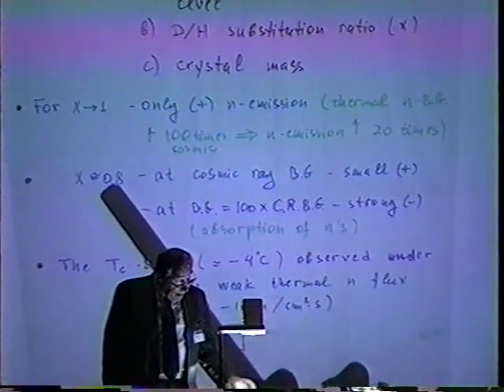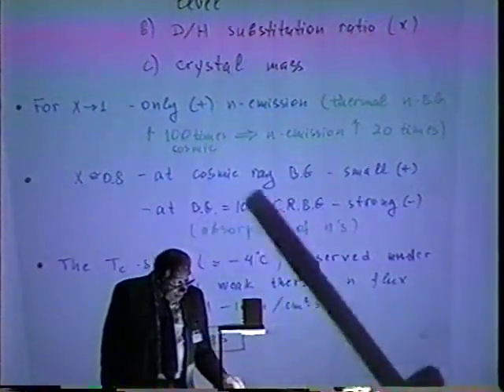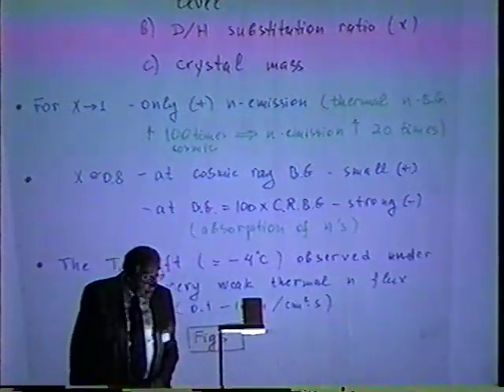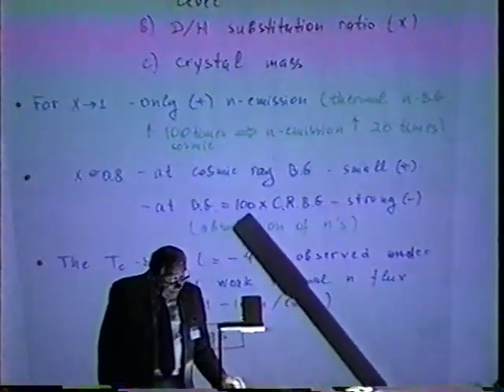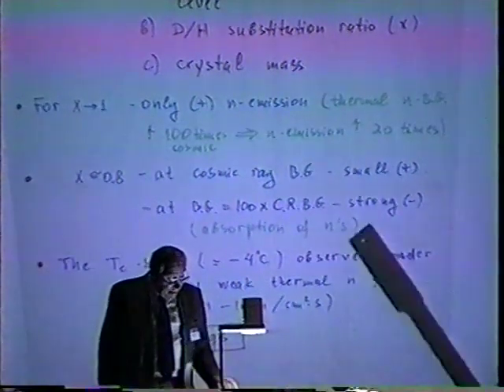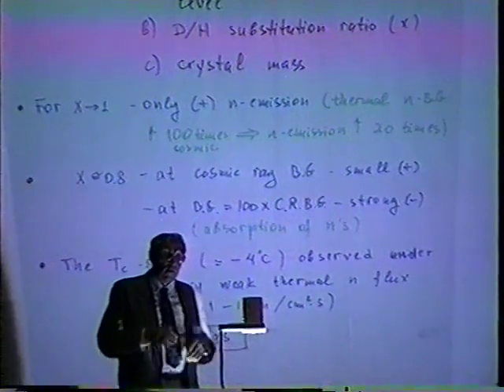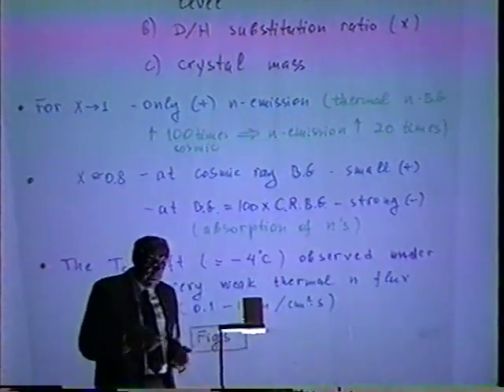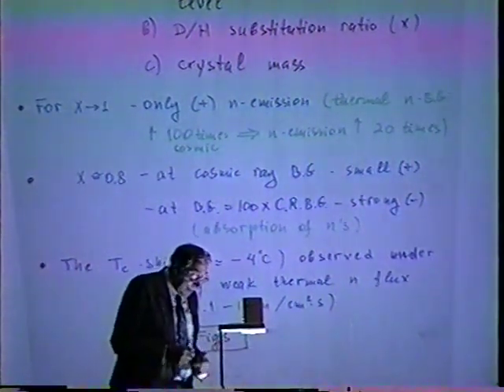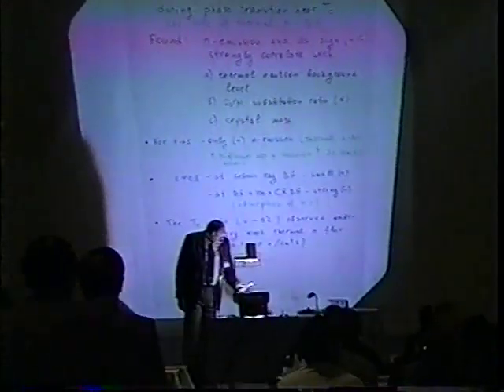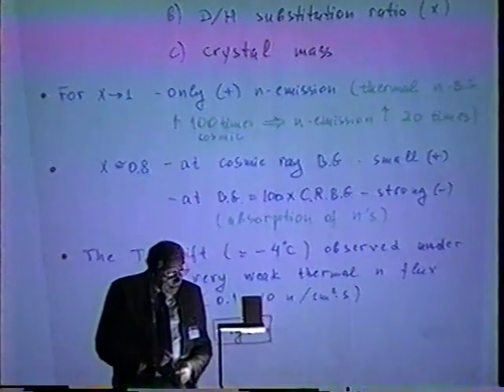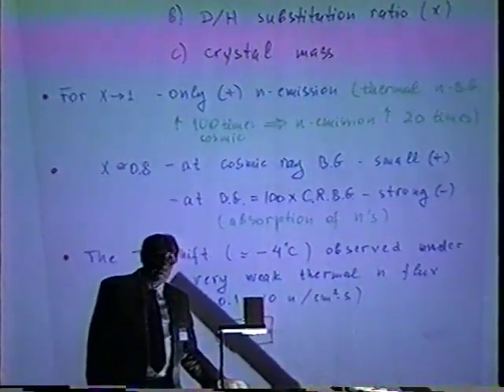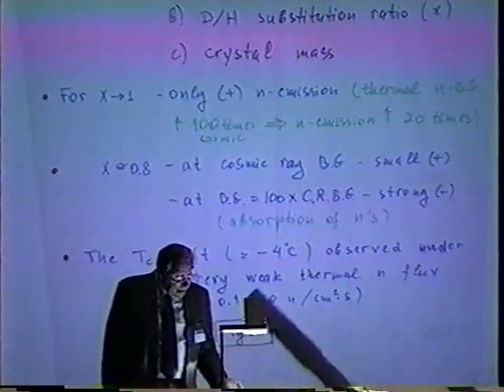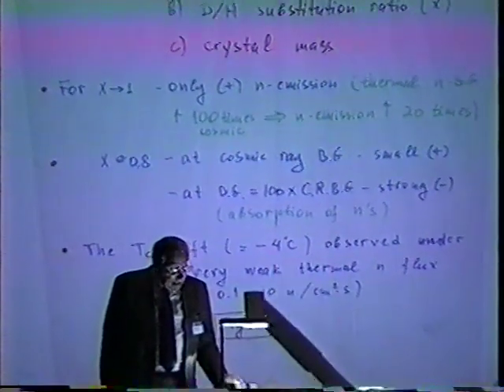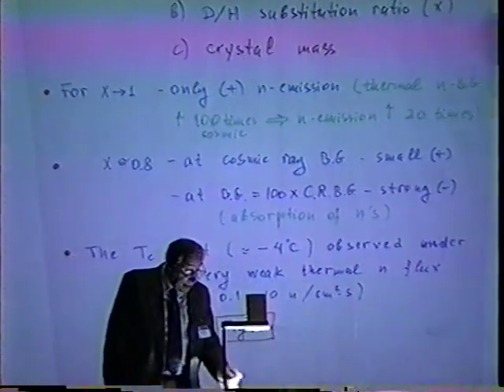At a smaller x equal to 0.8, and at cosmic ray background, they observed a very small, practically negligible effect. And at a background about 100 times larger than cosmic ray background, they observed a strong negative effect. It means that there is no excess of neutrons in comparison with the non-irradiated sample, but quite the opposite. There is a lack of fast neutrons. They also observed a very interesting, rather amazing feature: a shift in the value of the Curie temperature, lowered by about 4 degrees, when they used weak irradiation of their sample.